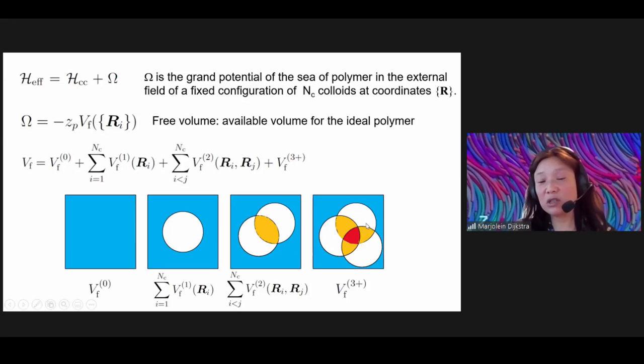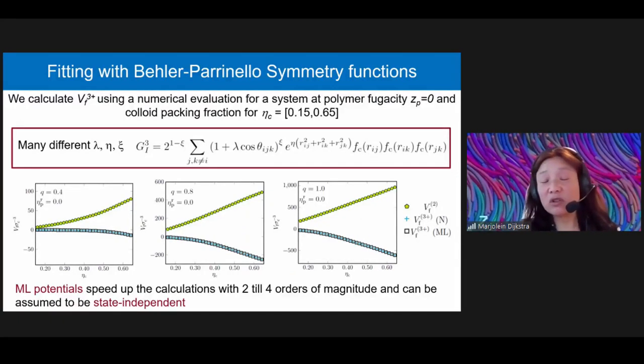The three and higher body terms are these very irregular overlaps of all these depletion zones, and they can only be calculated numerically. So that's what we do. All these three-body and higher-body terms, we just calculate numerically using a numerical grid. We do that for many different colloid configurations at many different colloid packing fractions at a zero fugacity of the polymers, and then we fit it with these Behler-Parrinello symmetry functions. And so if we compare then the three and higher body interactions, these are denoted by these blue symbols, and compare that with the machine learning fit, we find excellent agreement between the machine learning fit and the numerical evaluation of these many-body potentials.